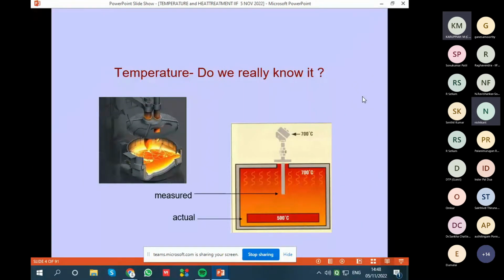So as I told you 2 minutes back, whatever we measure, we standardize on that. If we measure 700 and standardize our process, actually the temperature could be 500. So we would like to measure the temperature as close as possible to the job and make sure that what we are measuring is the correct temperature. So this will be the attempt to help you in doing that.